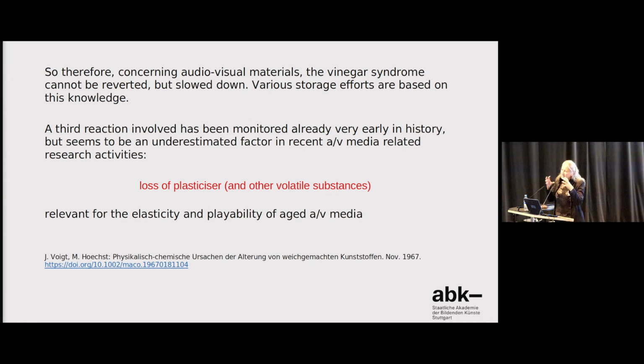And the other reaction: the more the chains break, the more volatile substances, like for example plasticizers, can evaporate. And this makes the material even more brittle. You have the breaking of the chains, and additionally, this opens the way for evaporation of plasticizers. This reaction was very well understood in the 1960s. So 1967, there is a basic literature which I would recommend to everybody from Mr. Voigt and Mr. Höchst, Physikalisch-chemische Ursachen der Alterung von weichgemachten Kunststoffen. In this publication, they explain in detail how the evaporation goes on.